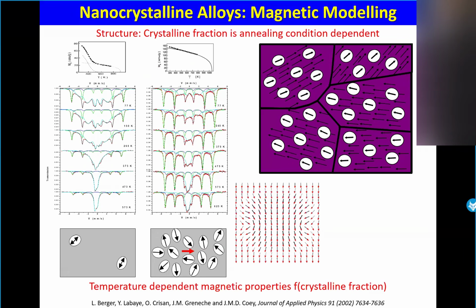It is possible also to discuss the systems which contain a low content of nanograins. So when you are at high temperature, nanograins are rather far apart, they cannot interact. So you have some fluctuation. They are superparamagnetic. But when you increase the number of nanograins, they will interact because they are rather close to each other. In addition, what you can see is that the amorphous matrix is not perfectly paramagnetic because you will create a polarization of the magnetic moments of the matrix through those of the grains. And it is not possible to observe this by other techniques.